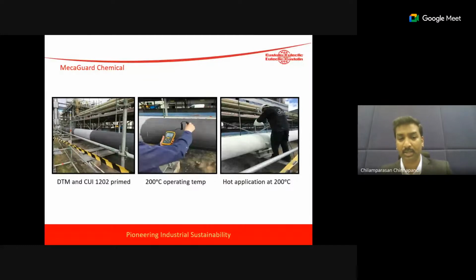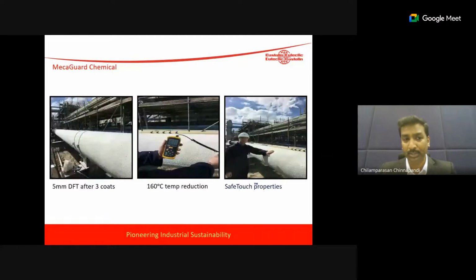And this is one of the unique products where corrosion under insulation coating can be applied on site, online. For example, the temperature of the current ongoing pipeline is 200 degrees, and our product can be just primed and hot application can be performed. We have done a 5 mm coating, which is 3 coats, and it reduces the temperature to 160 degrees outside. Internally, the temperature will be as needed for the system. Outside, you can have a safe touch of the pipe.